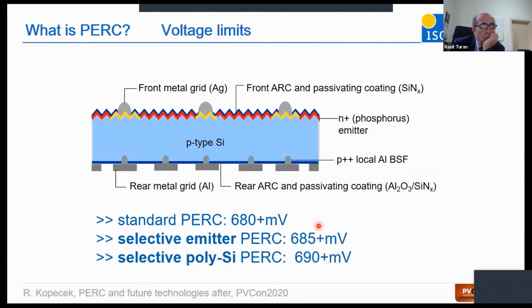The largest drawback, I would say, of PERC at the moment is that the efficiency is coming to its limits, and in standard PERC you have the possibility to go, let's say, to 680 millivolt or a little bit higher. When you are implementing selective emitters, you can go to 685 millivolt. And then with the selective polysilicon, which is not very easy, and that's why maybe also IBC concepts on P-type could be interesting. But even if you implement selective polysilicon, then you can reach close to 700 millivolt, but not very much higher. And that's why N-type concepts are getting more and more interesting.